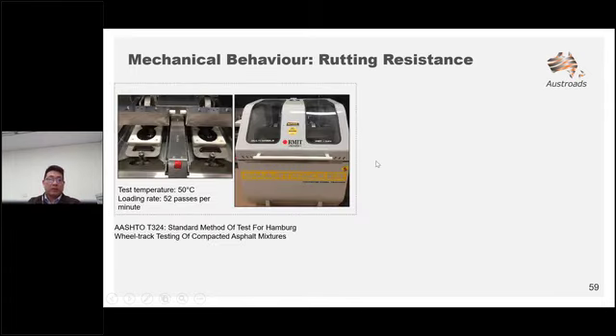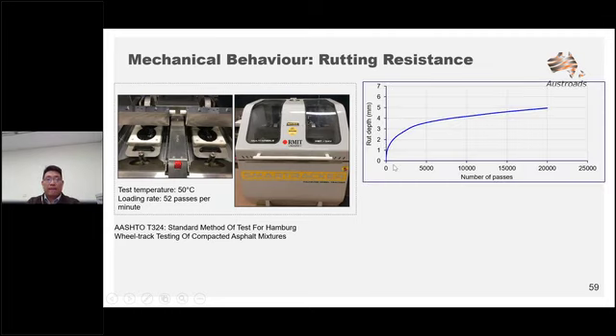So the next mechanical behavior we look into is rutting resistance. The test was run at 50 degrees Celsius, with a loading rate of 52 passes per minute. During the test, the rut depth and the number of passes were recorded, and we use the value of the rut depth at the end of the test, which was 20,000 passes, as the indicator of rutting resistance, to compare the performance between asphalt mixes.